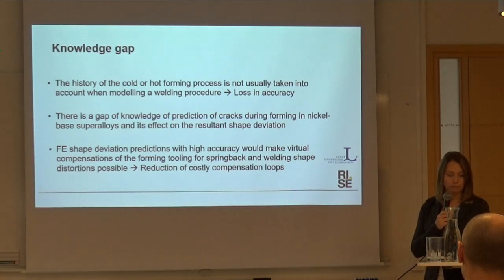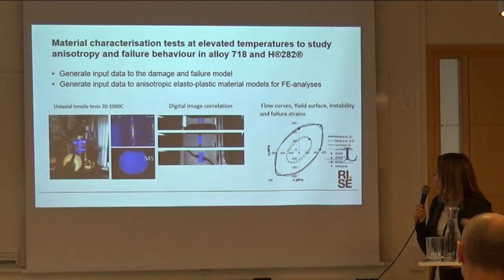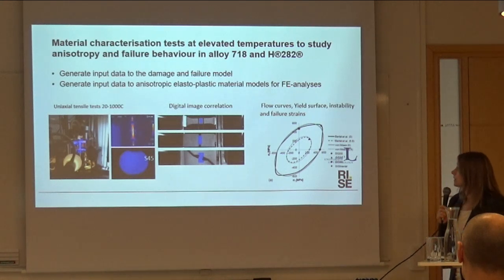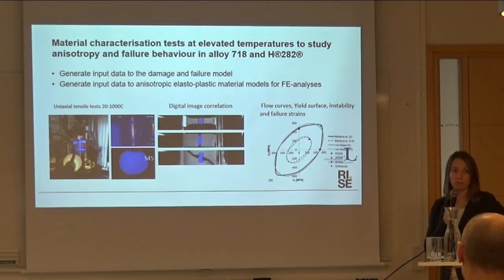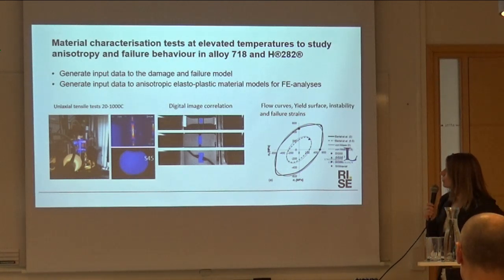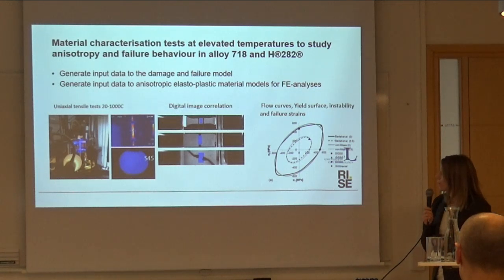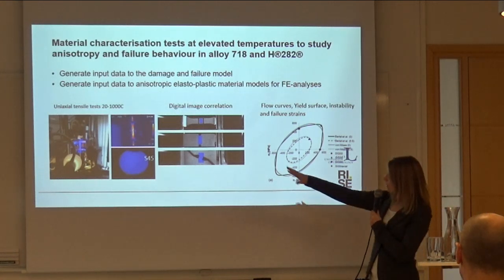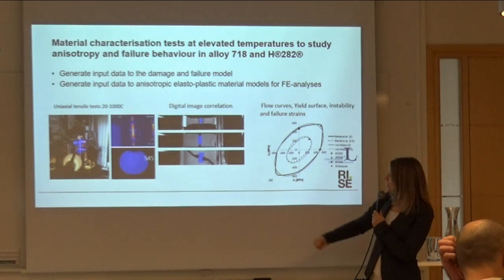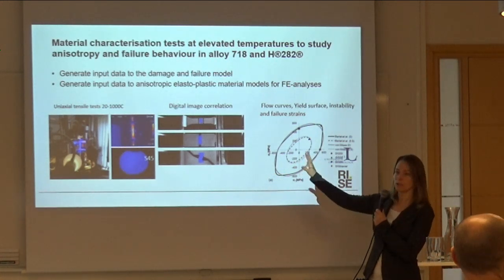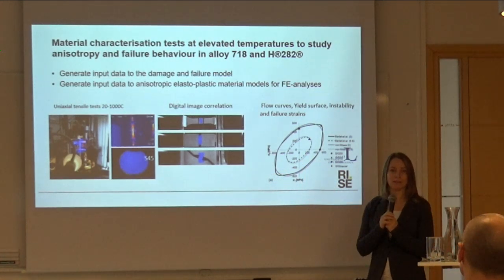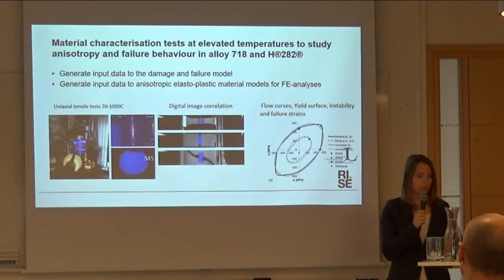In our lab we work a lot with material characterization methods where we can test the material properties at high temperatures, from room temperature up to over 1000 degrees C. And we work with tensile tests, biaxial tests, and different types of shear tests where we can study damage and failure properties in materials.